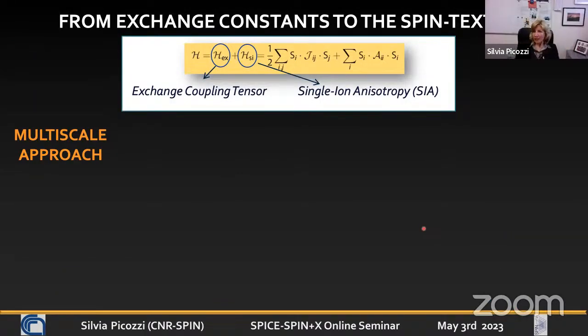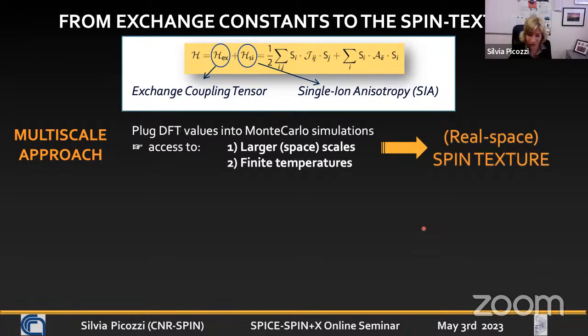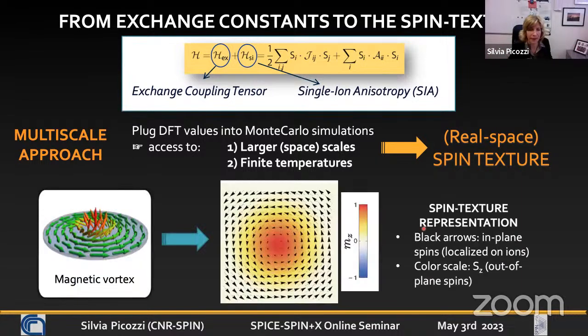So now, with DFT we can do only small systems and we can look at T equals 0. So to approach finite size, finite temperature, and also larger systems, we did Monte Carlo, which means that we evaluated the parameters from DFT, then we got our spin Hamiltonian. By means of Monte Carlo, we basically got the spin configuration as a function of temperature.